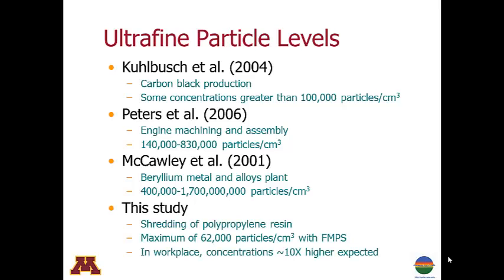In this study, our maximum concentration observed with the plain resin using the FMPS was only 62,000 particles per cubic centimeter, which was lower than any of the maximum concentrations from the other papers. In a real workplace where plastics are being shredded by a larger machine at a faster pace, we anticipate that concentrations might be about 10 times higher than in this experimental study. Even with this adjustment, number concentrations produced by shredding of plastics would not be out of line with what has been observed in other operations that may generate airborne nanoparticles.